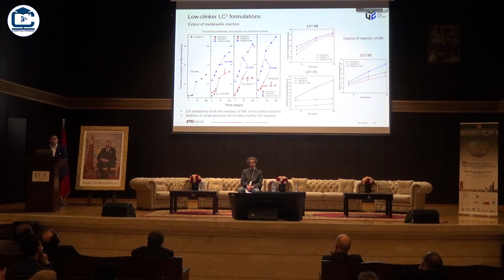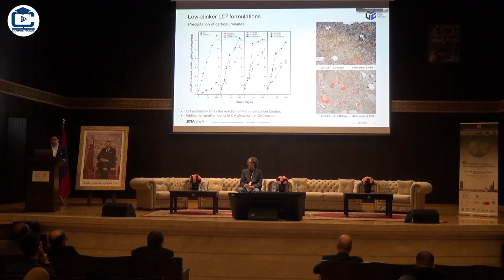So basically, the addition of Portlandite in LC350 doesn't make any difference because this system is not limited by Portlandite availability. There is plenty of Portlandite to make it react. But in LC325 and LC315, we are limited by this, and by using this admixture. And this will be a keyword during the rest of the presentation. By using this accelerator admixture to boost the reaction, we can actually recover a lot of this reactivity of metakaolin.